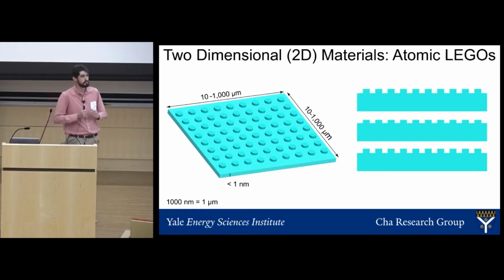It's very difficult to break the layers in half because the atoms within those layers are very strongly associated with each other. But we can take two layers and put them on top of each other and they'll stick together, just like you can stick two Lego bricks together. But also the interlayer interactions are quite weak, which means that we can easily peel off layers from one another, just the way you can unstick two Lego bricks that you've stuck together.